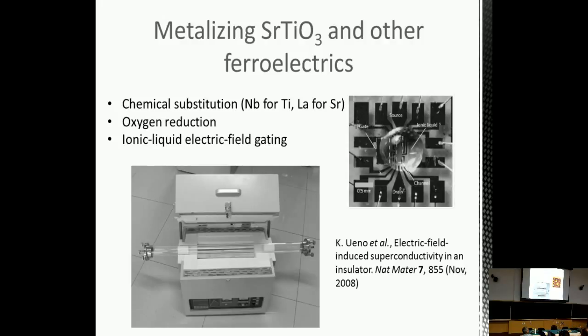So now we want to introduce electrons into the lattice and see what happens to the electrons. We use strontium titanate because it's well known that you can make this metallic. And one of the ways you can do that is just by heating it in a very good vacuum at high temperatures, and then oxygen comes out of the lattice. And oxygen vacancies lead to additional electrons which form bands.